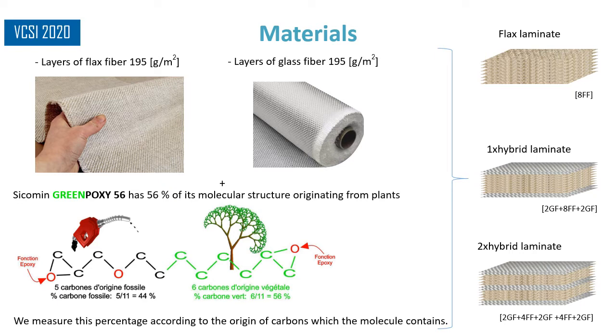Three laminate configurations were prepared by a layup technique: laminate with 8 layers of flax fibers; laminate with 2 layers of fiberglass on each side and 8 layers of flax fiber in the middle, denominated 1X hybrid; and laminate with 2 layers of fiberglass on each side, 8 layers of flax fiber between these, and 2 more layers of fiberglass in the middle of the flax fibers, denominated 2X hybrid.